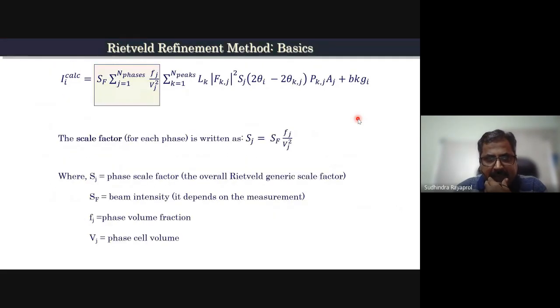Okay, so if you just look at that, one is the scale factor. The scale factor actually is given by this equation. What it means is that it tells the program from which part of the diffraction pattern you have to start, assuming this, you have to scale the intensity. So then only the intensities will match. Scale is something which we refine all the time, so that any changes should not affect the intensities. So the intensities will be proper if our starting point is correct. So that is our scale value. So it will put the observed and the calculated pattern on the same scale based on this information.